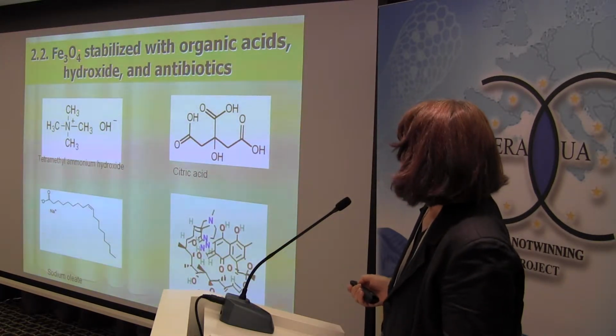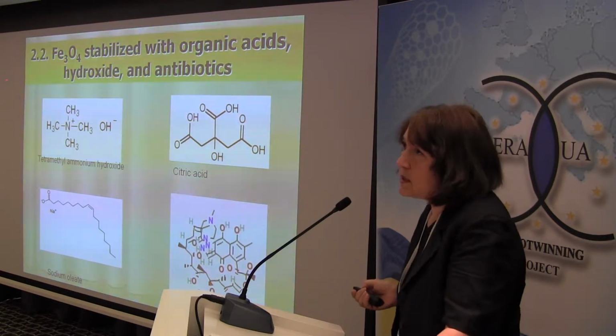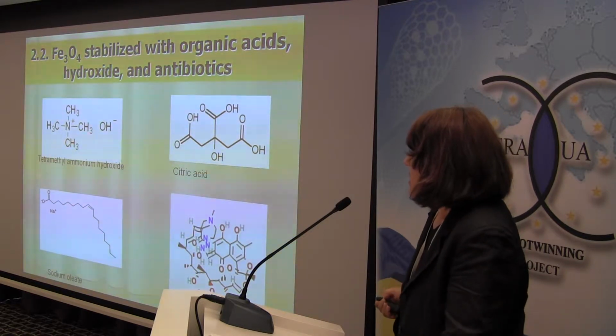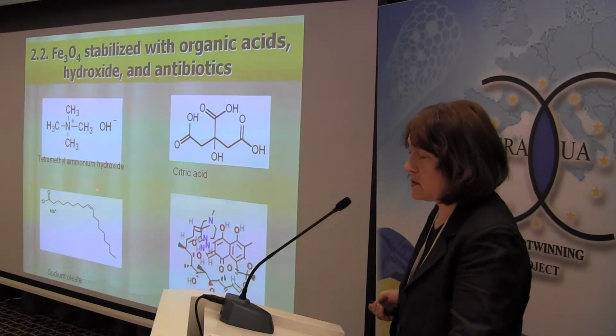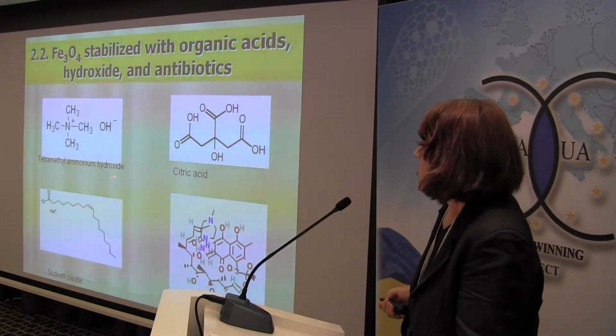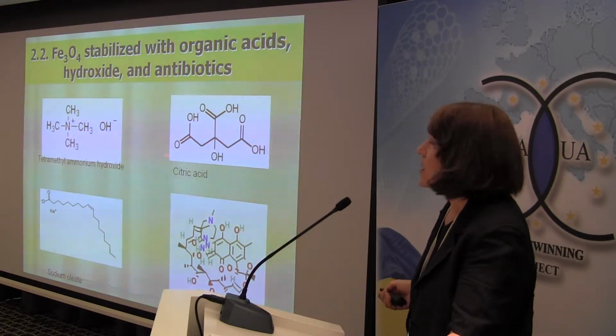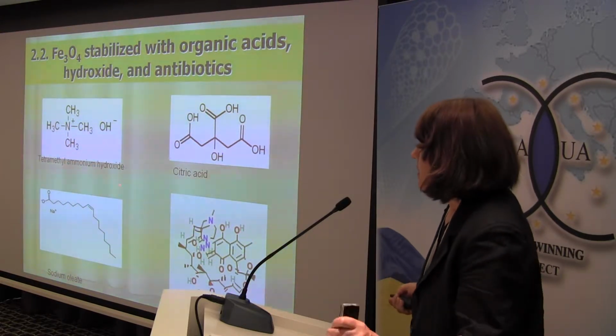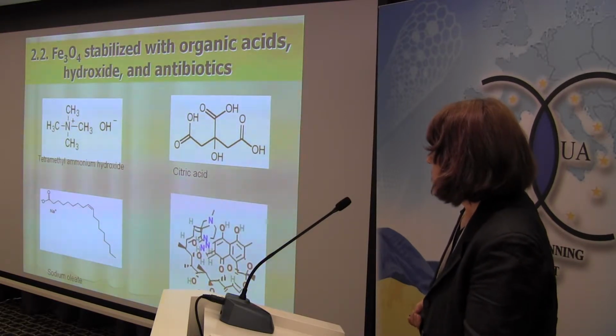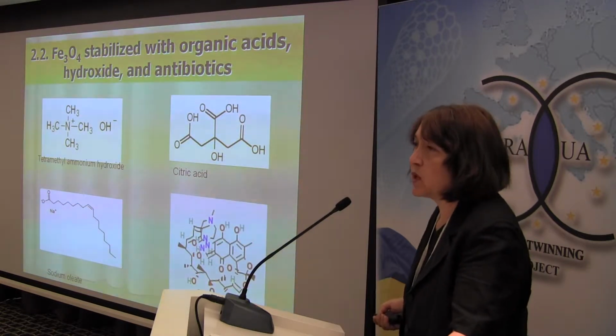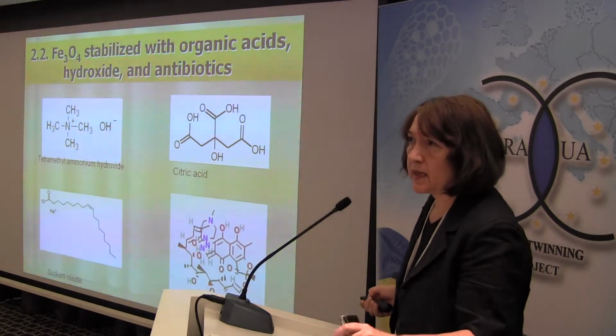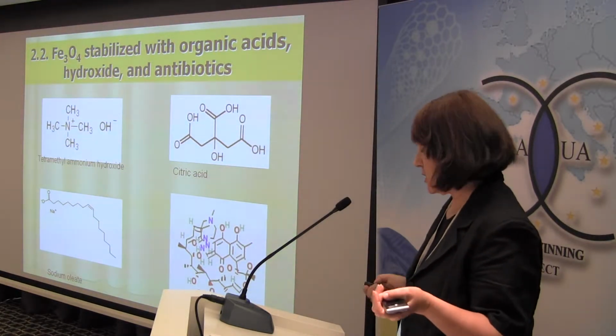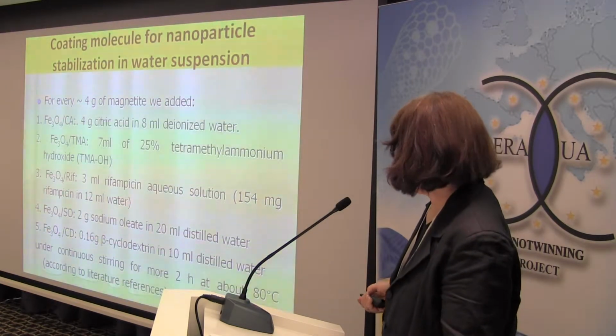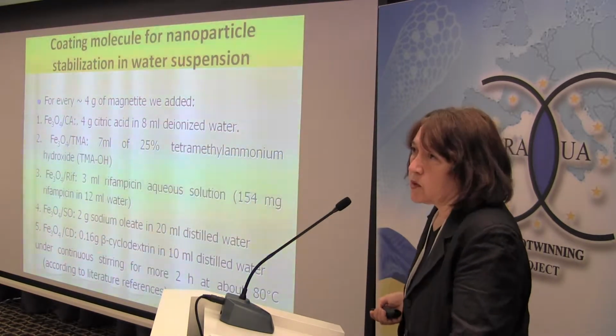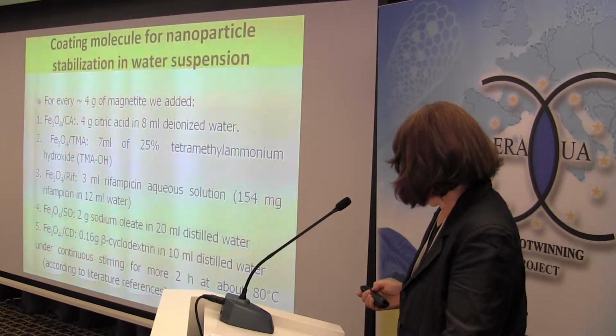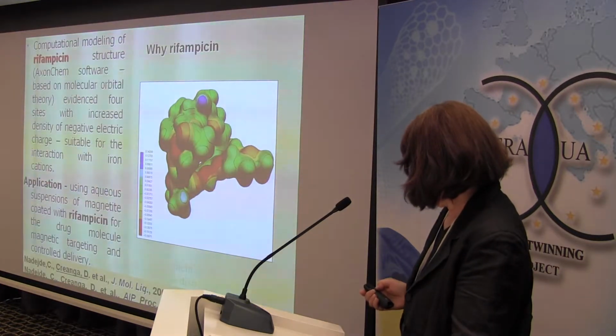The other category, the magnetite nanoparticles stabilized in water, was focused on the nature of the organic coating shell. Citric acid and tetramethylammonium hydroxide are also known from literature. We prepared those fluids to have a comparison reference, and also sodium oleate, but the main goal was to see if some antibiotics or other molecules with medical interest could be directly attached, and not grafted, on the coating shell as usually is done. Here are the amounts of the molecule used to coat the nanoparticles. There is also a cyclodextrin that we studied.